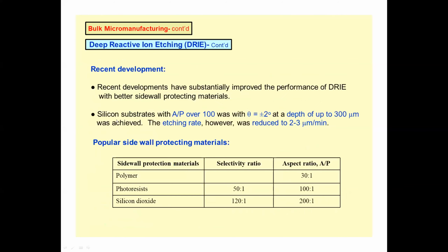Quite recently, DRIE with better sidewall protecting material, on a silicon substrate with an aspect ratio over 100, was achieved at a depth of 300 micrometers. Normally only LIGA would be capable of realizing this type of vertical structure, but with DRIE, because it is deep etching, you can create aspect ratios for, say, polymer of 30:1, photoresist 100:1, and silicon dioxide 200:1. So you can create much better aspect ratios.